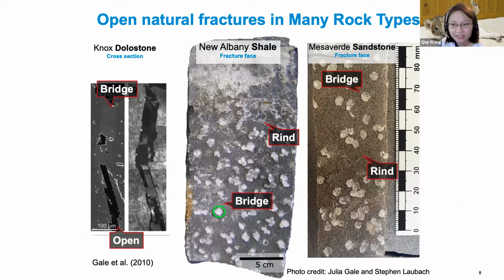Here, I'm just showing fracture cement in natural fractures in various rock types. So they do not just exist in sandstone. From left to right, we see cement bridges and open pore space in the fractured stone. And in this second picture, we are looking at the fracture face of a piece of core of the New Albany shale. We see the cement bridges are actually patches of minerals growing on the fracture surface with spaces in between. Those would be open pore space in the cross-sectional view. And we see a similar feature found in the Mesa Verde sandstone core example. We see patches of quartz growing on the fracture surface with space in between.